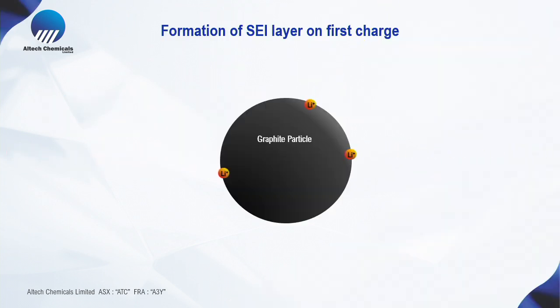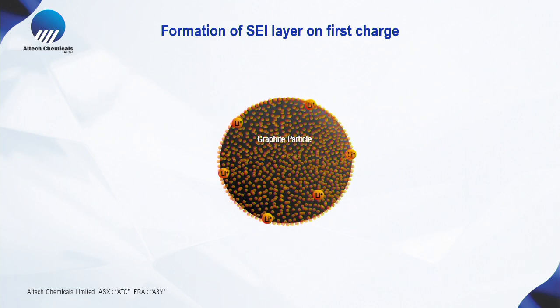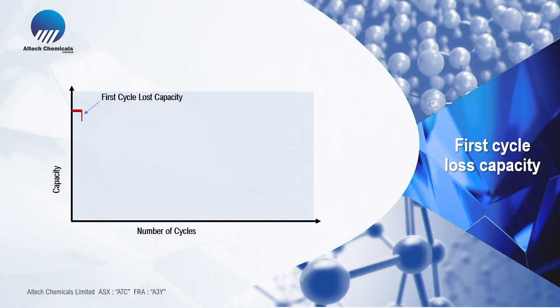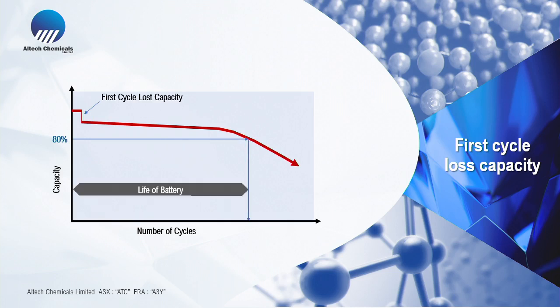So let's look on the molecular level at what happens. This is a graphite particle. When you first charge it, the lithium ions go across, and it starts to form an SEI layer. Now, if you look at the performance of a battery on a chart, this is what the first cycle loss capacity looks like. The capacity drops, and then you've got the life of the battery. At 80% level, that's the life of the lithium-ion battery. Okay, so my question to you is that if you can resolve this first cycle loss capacity, can you see that the battery capacity is going to be 8% higher before you get it, and also longer life. So this has been the challenge for the industry.